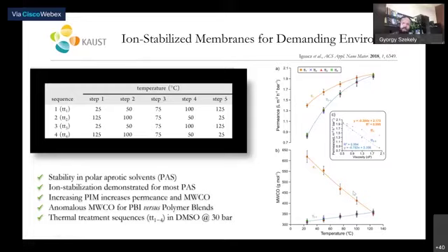So the conclusion here is that there is an initial compaction and change in structure at the beginning of this thermal treatment. So when you increase the temperature first, you get this performance profile, but when you decrease it, you don't get it back. You get basically a lower performance. But after that, this performance remains stable. Okay, so the most important thing for a membrane is to be reproducible. You always get the same data. So what we realized here is that if we can do a treatment at different temperatures, then we can fine-tune the properties of the membrane. And this is true for the selectivity here as well.